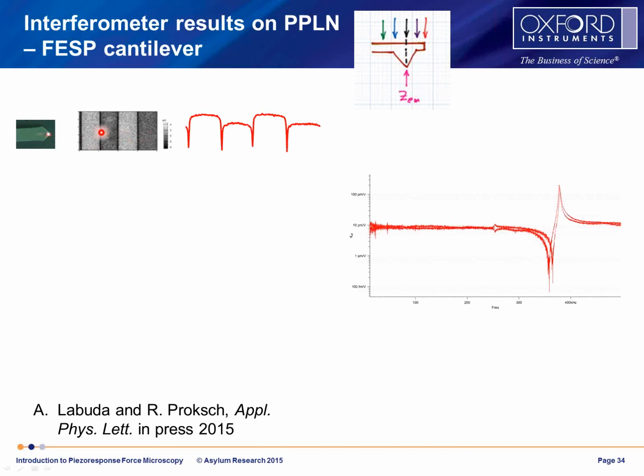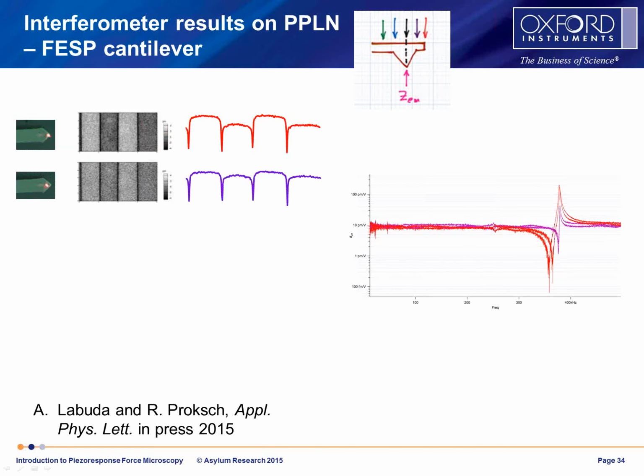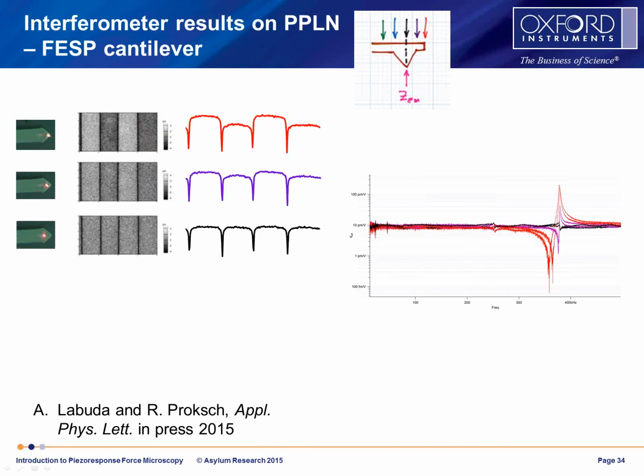So this is the domain image. This is a section through that. And then this is a tune going from somewhere around 0 to a little bit above 400 kilohertz, where the contact resonance is about 380 kilohertz. Now we're going to step that interferometer spot along, and you'll see as we go, there it moved back a little bit, moved back further.